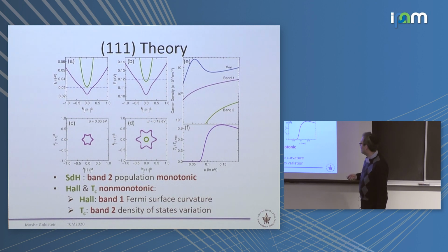Now, as for TC, again, it seems that superconductivity is somehow in the region where band 2 is important, and here we are less certain. Again, we did the same trick of just plugging in the density of states of band number 2 into the BCS formula, and it does give you some pretty shallow dome, because density of states is not exactly monotonic, but here again the density is monotonic. TC is not monotonic. It could be just because of variation of density of states. It could be other effects like in bulk STO, but in any case, it's not because of things going between the bands as in 100, because this is not happening. And indeed, the peak in TC is not correlated with anything in Shubnikov where there is no peak, and in anything in Hall where the peak is at a different place.